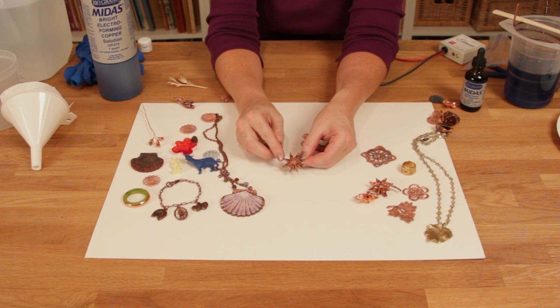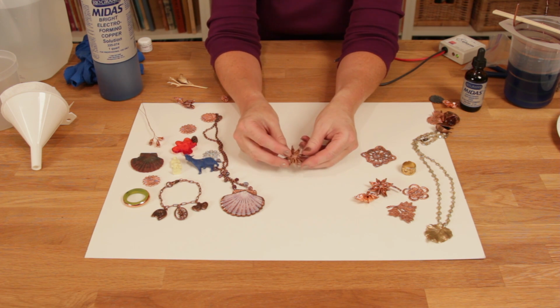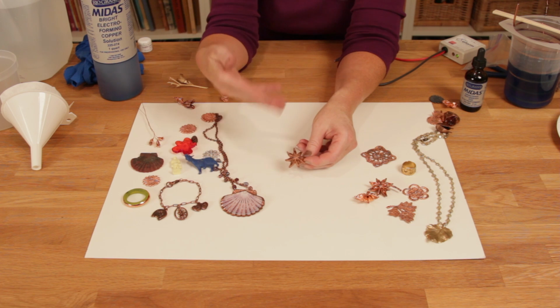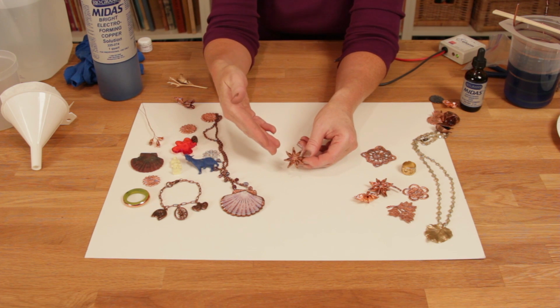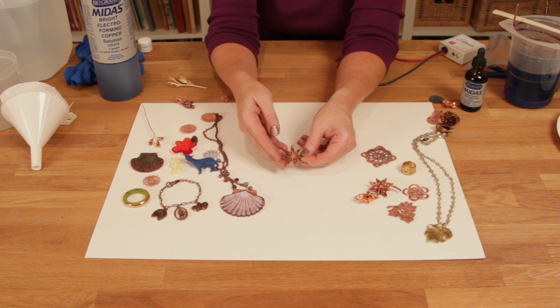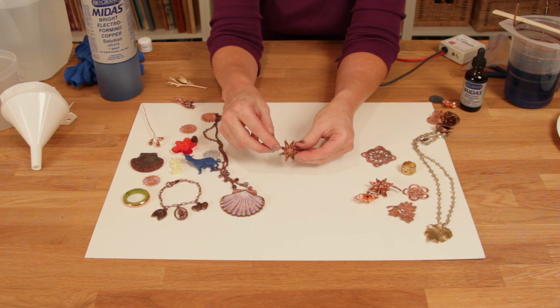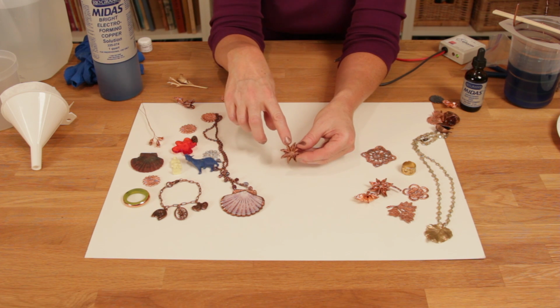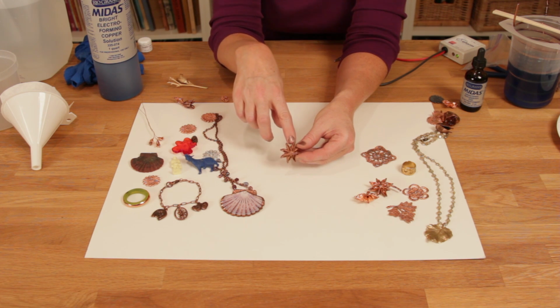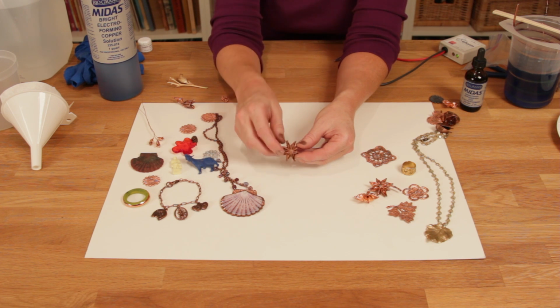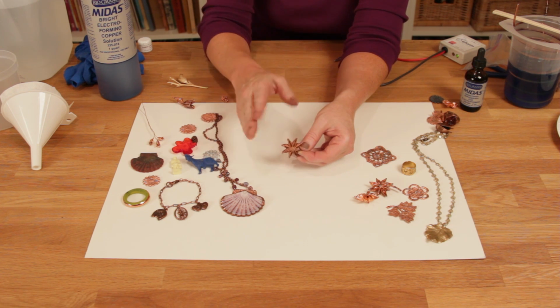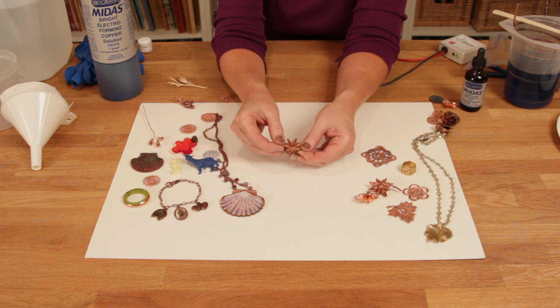After you've removed your piece from the electroforming solution and rinsed it off in distilled water, you may see the piece start to darken a little. That's just from oxidation that happens to fresh copper. You can put it in a pickle solution to shine up the copper. You can buff and polish it and treat it as any other copper. If you noticed a few black spots here and there, it may be that it didn't plate in those areas. So you simply reseal with some varnish, repaint with graphite, and then place back in the plating solution to cover with copper, and it will coat those areas just fine.